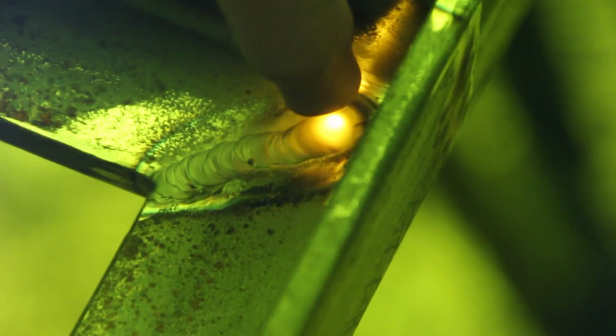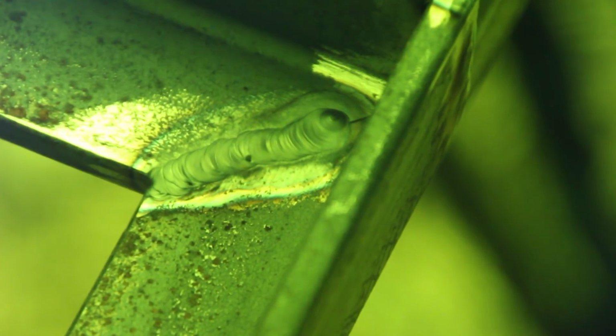Here I'm welding the butt joint on the inside of the corner, and I have the welding filter in front of the camera turned up a bit so you can see better. I'm dipping the rod about once a second, and this is at about 120 amps on the TIG torch. So all in all, I think this weld came out reasonably good. There's just in one spot a little bit of porosity, but nothing that'll cause a problem.